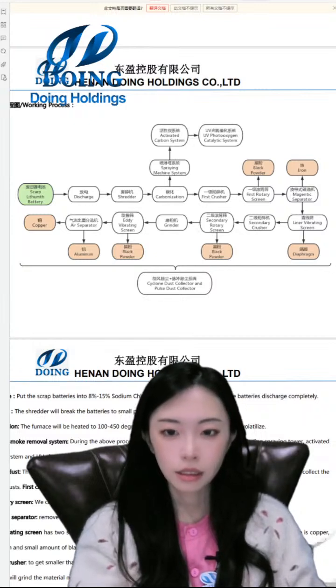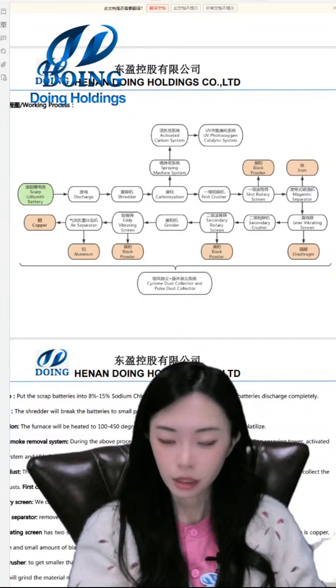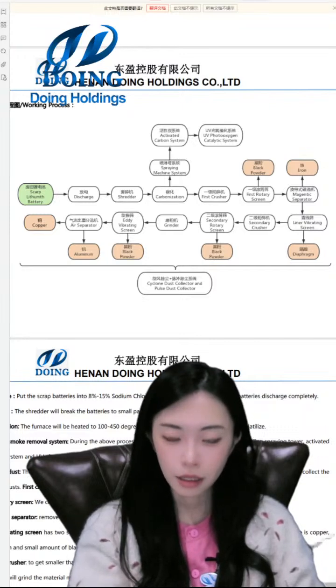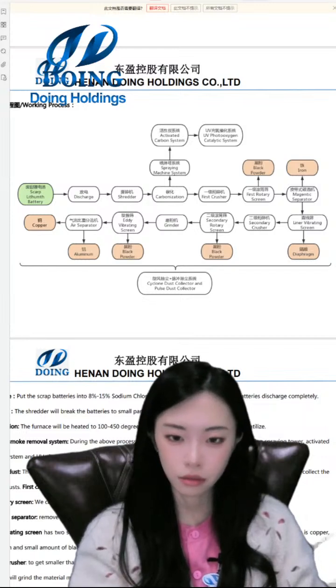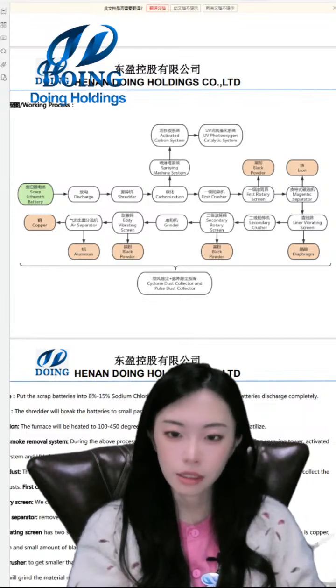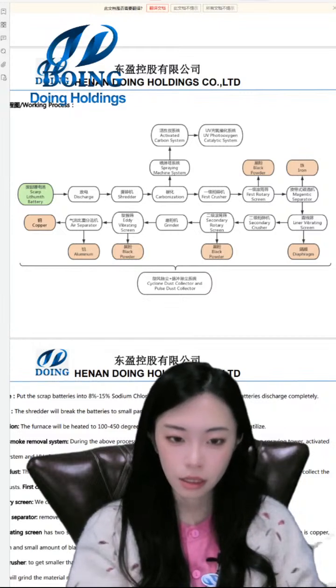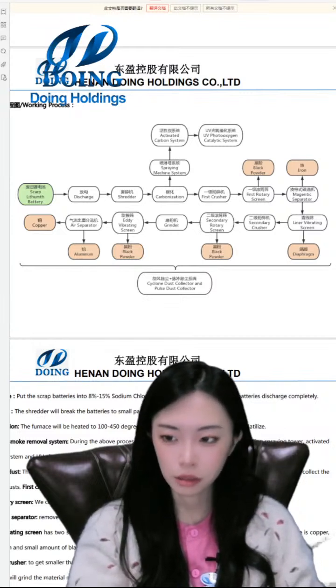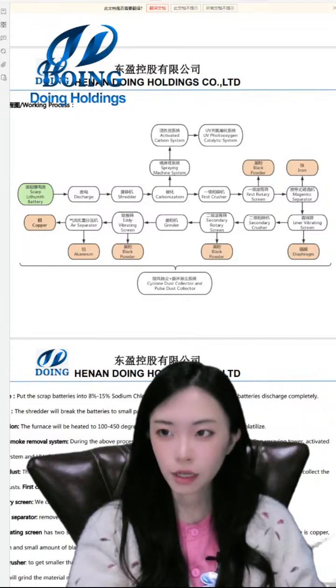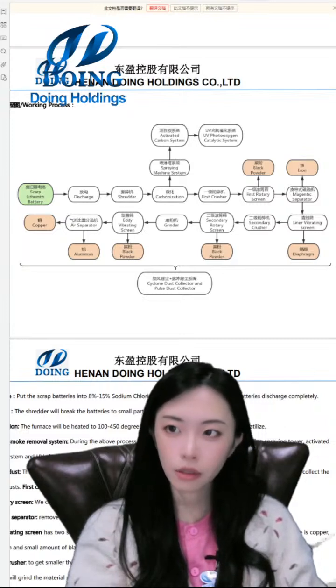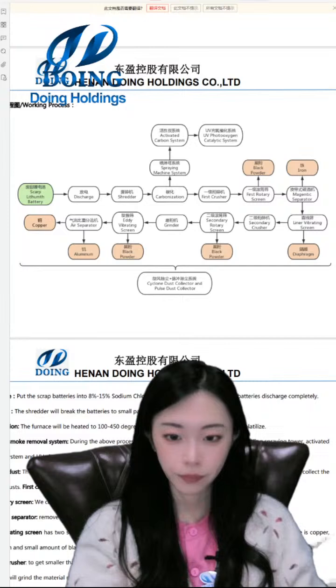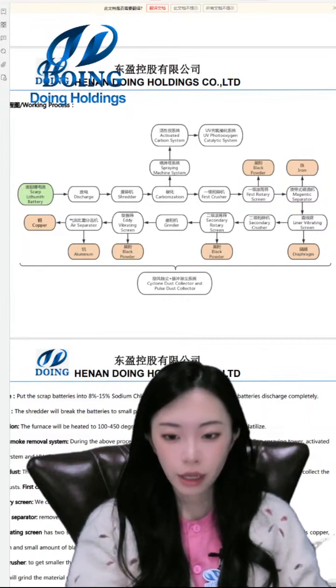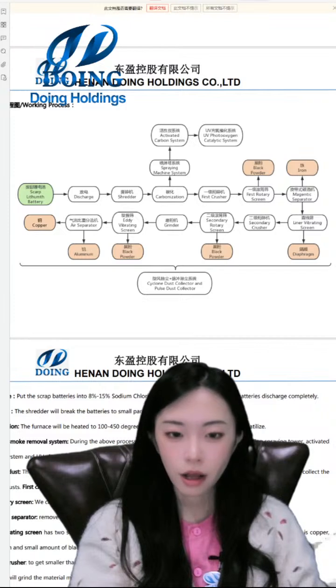This is to separate the carbon black. Through the 120 mesh rolling rotary screen, the qualified material is discharged through the screen holes. And the black powder here can be recovered at about 60 to 70%. This is the carbon black. And then we will go into the magnetic separator. This is to separate the iron from the particles.